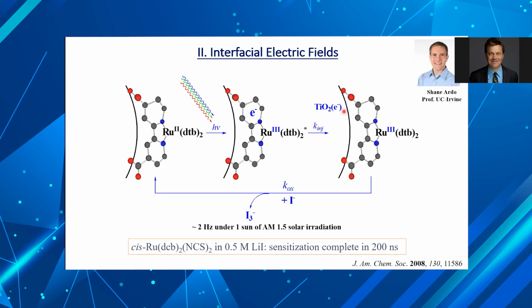At the short circuit condition, you try to pull those electrons out as quickly as you can. At open circuit, you just build up as many electrons. You move the quasi-Fermi level of the TiO2 up toward the vacuum level to generate a large photovoltage. But at the power point, where the product of current and voltage is a maximum, that's where you want the highest energy conversion.